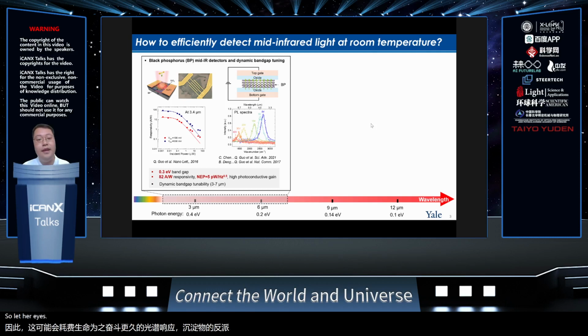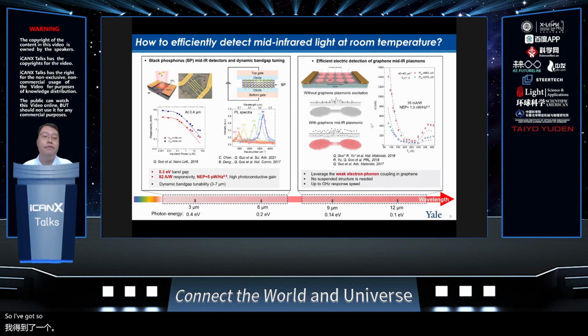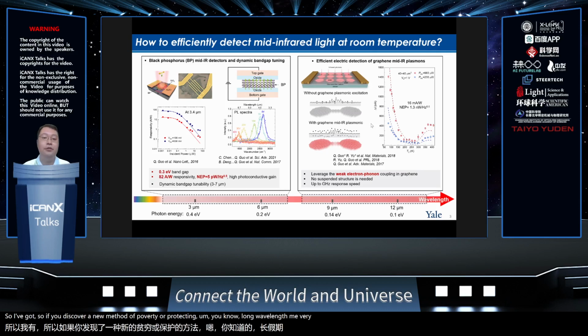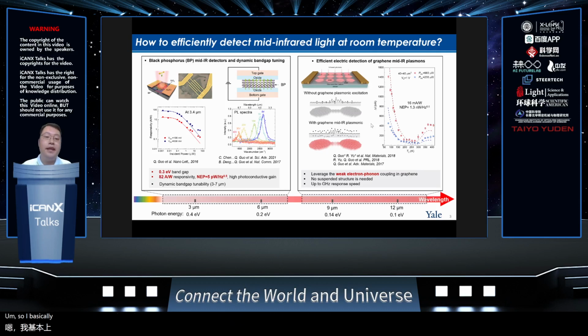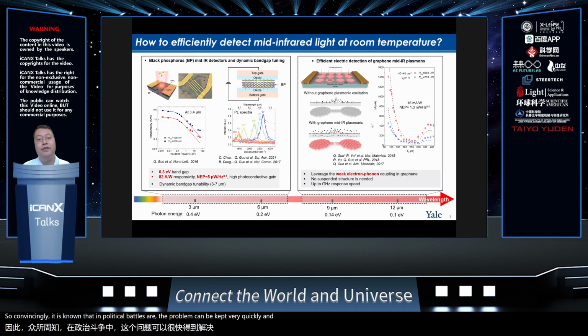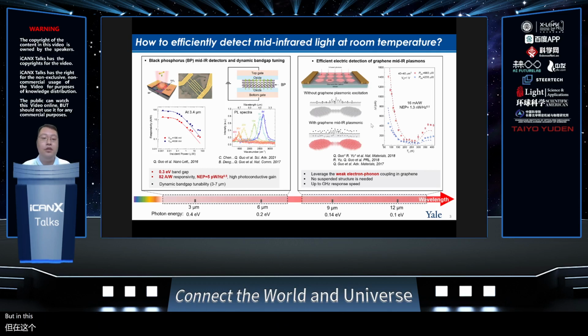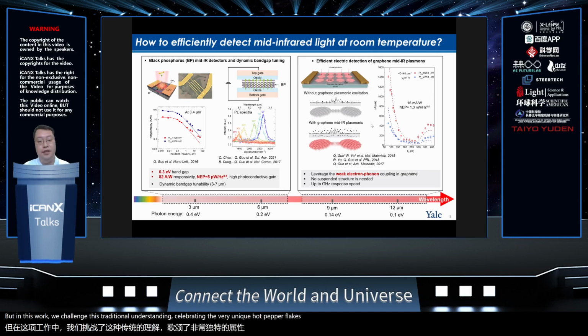Later, I entered an even more challenging regime, which is around 10 micron. I discovered a new method of detecting long-wavelength mid-wave photons. I convert long-wavelength mid-wave photons into the plasmon mode in graphene, and then read out the plasmon electrically by using the electrical transport properties of graphene nanoribbons. Conventionally, it is known that in conventional metals, the plasmon decays very quickly, and it's very difficult to harvest them. But in this work, we challenge this traditional understanding by leveraging the very unique hot carrier physics in graphene.